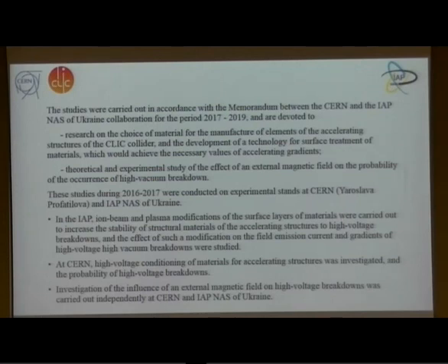In the Institute of Applied Physics, ion beam and plasma modification of the surface layers of materials were carried out to increase the stability of structural materials of the accelerating structures to high voltage breakdown, and the effect of such modification on the field emission current and gradients of high voltage and high vacuum breakdown were studied.